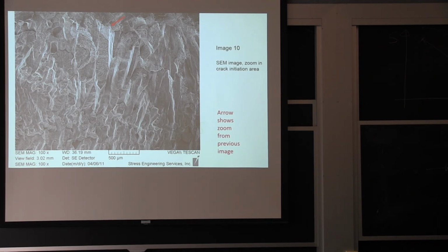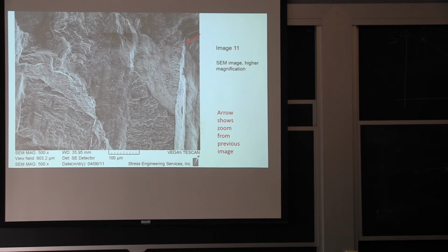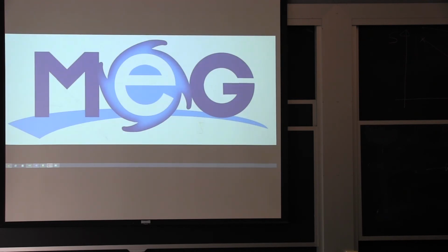And it's a reason why sometimes with hydrogen-induced cracking or stress corrosion cracking, the growth of the crack is steady. It doesn't vary very much with the load applied because it's the time to get the hydrogen at the location that determines cracking. So it's a constant rate over time in this zone. So when we do this flash welding, we avoid all these issues.